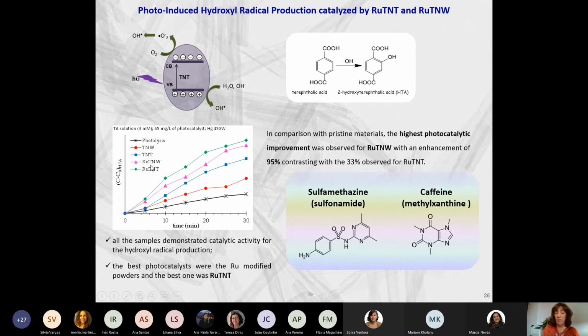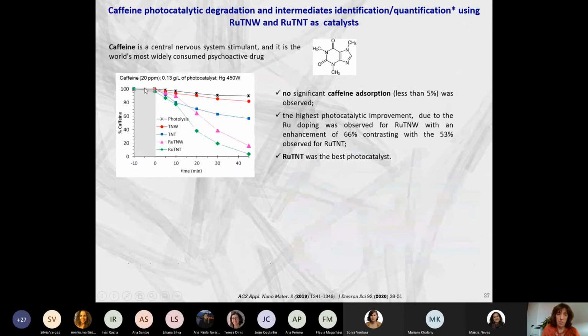And now that we know that we have chances to have good photocatalyst materials, it's time to try to use these materials for the degradation of some other pollutants. In this case, we tried caffeine and sulfametazine molecules. As you can see here, once again, we have better performance, photocatalytic performance for the sample ruthenium titanate nanotubes. And this one is also very interesting. And if we think a little bit, I don't know if you remember, but this sample is not the one that has higher surface area, but is the best one. Well, why? Well, we don't know, probably we know, but we need to think a little bit more about this, why the nanotubes are better than nanowires.